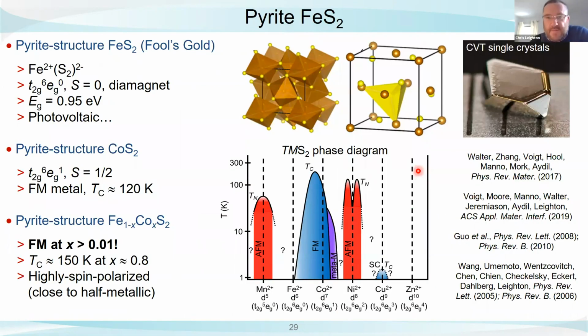So this drove us to thinking about pyrite iron disulfide. You may be familiar with this material. It's fool's gold. You may know the crystal structure. You may know the obviously goldish appearance of this material. You might also realize that chemically it's a little bit interesting because it's iron 2+, sulfur 2, 2-. So that gives you a t2g6 eg0 electronic configuration. Its S equals 0. Rigorously, it is a diamagnet. This has been known for decades. And it's actually a 1 electron volt band gap semiconductor.